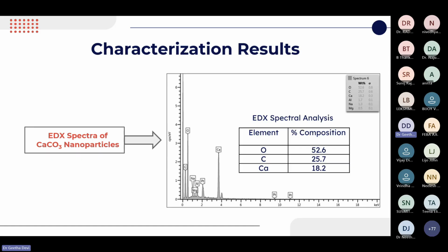It is seen that oxygen is 52.6%, carbon 25.7%, and calcium is 18.2%. This also shows the high purity of the nanoparticle.